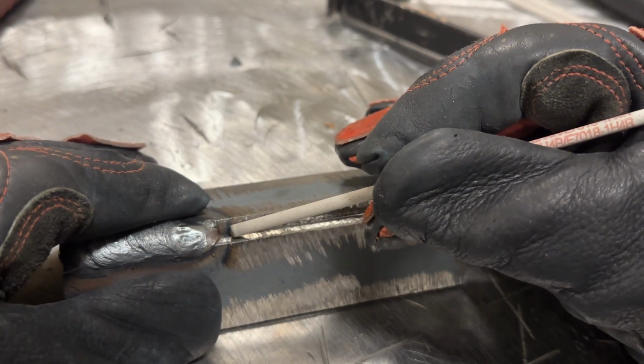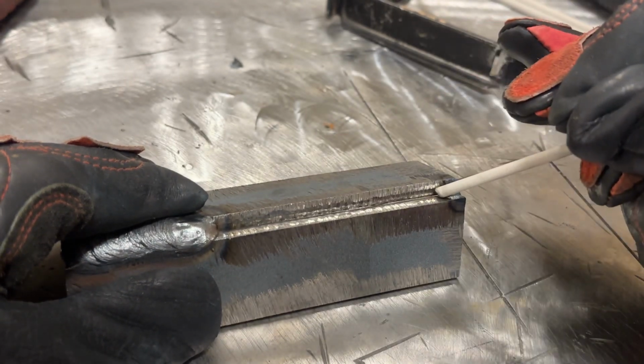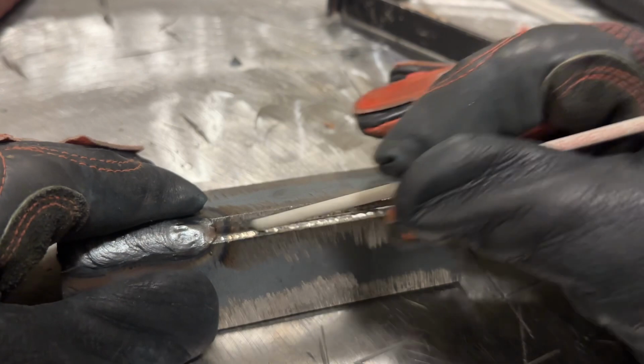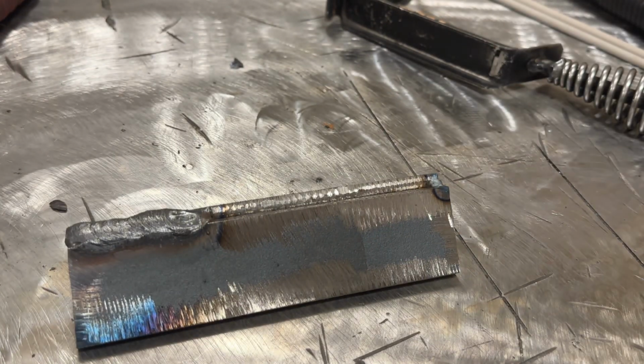So I'm gonna crank it up a little bit, and I'll weld another third of this and we'll look at it. Couple quick things I'm gonna mention. One is my arc gap is a little bit too long on this, and I think my amperage is a little bit on the high side. You can see a fair amount of molten balls popping out of there. But it did run pretty good until the end, and the molten pool stayed below the top edge of the plate.